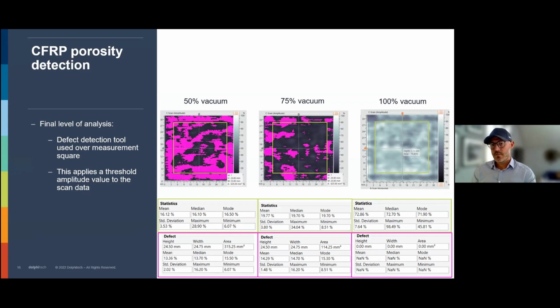But notice that you can see a lot of the variations of the porosity. Imagine you had a single element probe and you just get one number here. If you hit this area here that is gray, you might get an approved value. But as you can see all the variations here, you have a lot more data. And you can say that you can approve 30% pink inside that square, for example. So the point here is to demonstrate that it's an easy to use tool and technology, but with all this data, we also have a lot of advanced features that are possible.